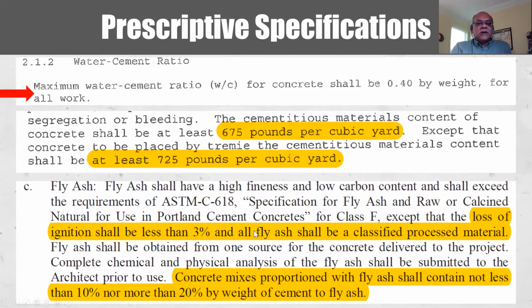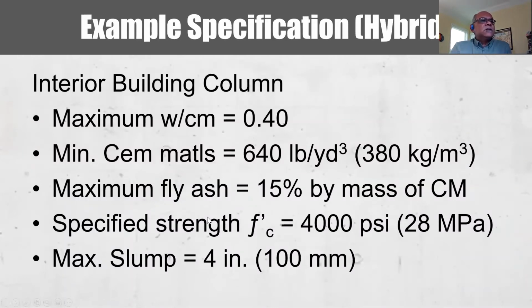You might see requirements where there are additional restrictions on the type of SCMs, like fly ash, that can be used in a project beyond what the ASTM specification dictates, in which case you might have an issue that exacerbates the already bad supply problem that we have with some of these supplementary cementing materials. And then you might see maximum limits on the SCMs that are put in specification on concrete mixtures. And like Lionel mentioned before, there are different applications where those would be necessary and maybe more than your maximum limit. This is just a simple example, and not an unrealistic example, of what we might see in a hybrid, let's say, concrete specification.